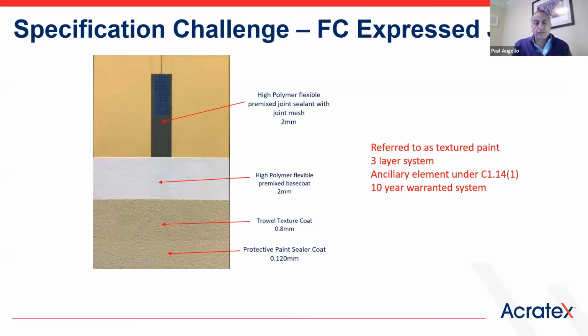So this is what we're looking at in summary. A typical reinforced fibre cement sheet system. You've got the joint system there, which has the fiberglass reinforced mesh. You've got a levelling skin coat, around 2 millimetres, and then you've got the textured layer coat for aesthetics. And then you've got that protective layer coat that sits over the top. And if it's interpreted the right way, you've got a fit for purpose system. You've got a DTS solution with a warranty system, and it will be exempt under C1.14, in our opinion.